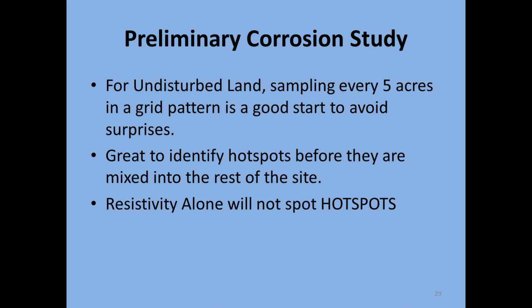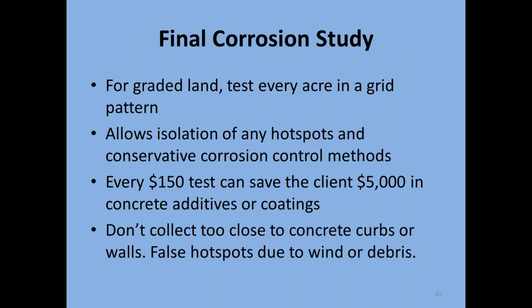Yeah. So like I said, resistivity alone will not spot the hot spot. So just going out there and doing the 1 and 4 pin testing is not the way to figure it out, especially in the summer. You're just lying to yourself. So that's something to keep in mind.